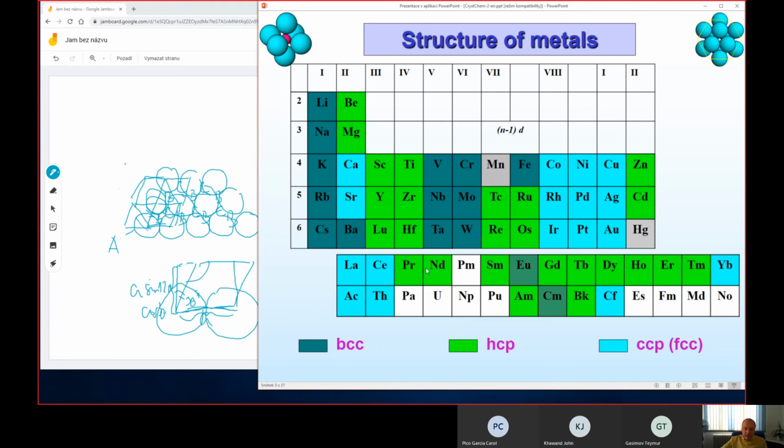In some cases, like for hexagonal structures, we can have a more complex arrangement. For instance, americium has the stacking pattern ABAC, ABAC, so the c parameter is longer compared to the basic hexagonal close packing, but still it is denoted here as HCP.